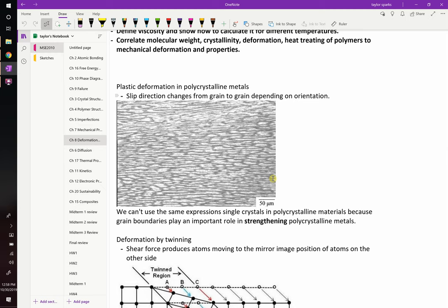But then they pass this through a hot roller, right? This is how they make tin foil, aluminum foil. They start out with a big block of aluminum, and then they pass it through hot rollers that squish it a little bit as it goes back and forth through it, and it gets thinner and thinner and thinner. And they keep on heating it up in this process. If you were to zoom in on the structure, you'd notice that it starts to look like this. The grains are really long and stretched out. Their microstructure has changed quite a bit.